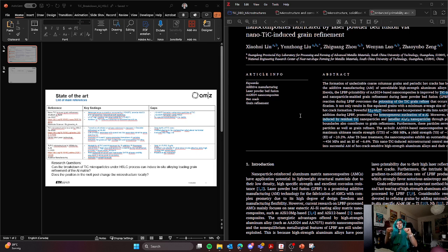And the last paper is really titanium and titanium carbide microstructure in aluminium, silicon, magnesium. It's something I'm very interested in because it's the exact same material I'm using, except that they use titanium particles with titanium carbide nanoparticles around. So again, it's nanoparticles. And they use a 1:1 ratio of titanium carbide, and it's only 2 weight%. Again, I use micro particles of titanium carbide, 30 volume%.